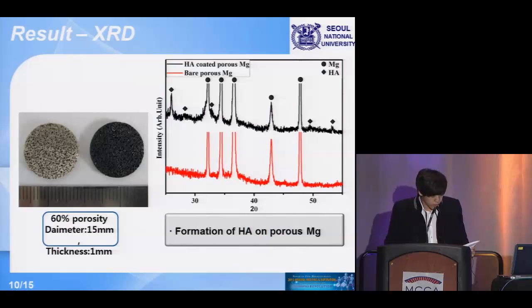And after the coating procedure, the porous magnesium color changes to light black. And by the X-ray result, you can see that hydroxyapatite has been formed on the surface of the porous magnesium.